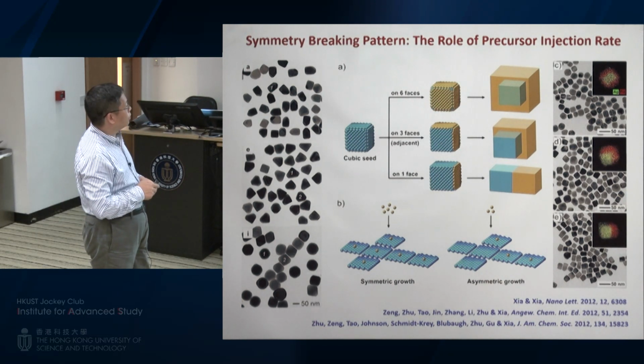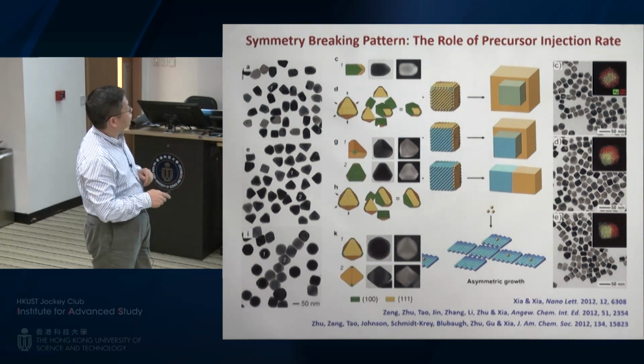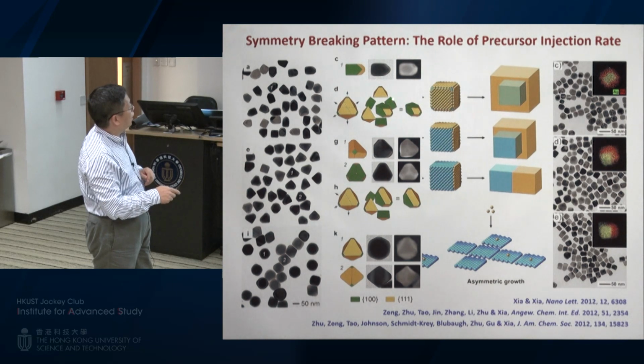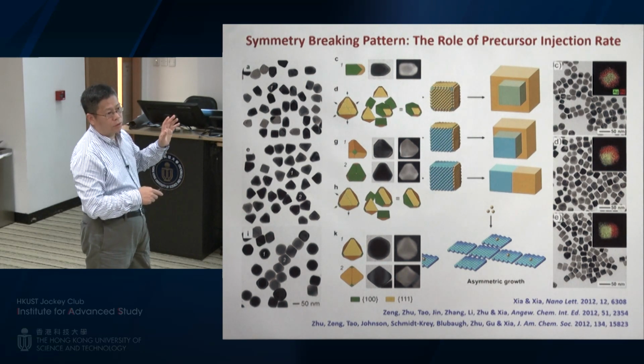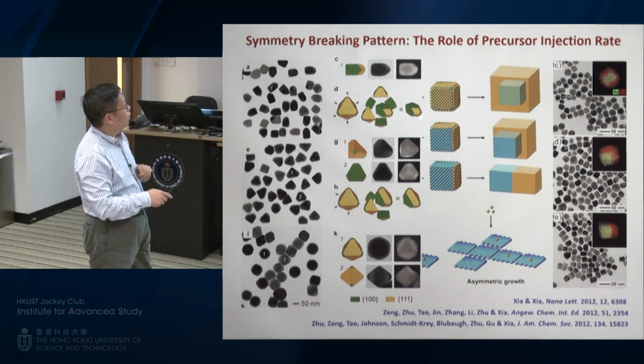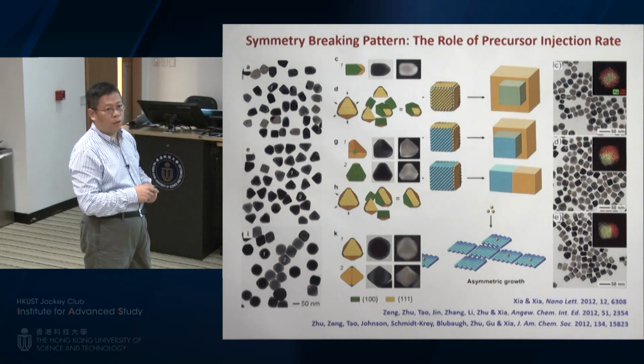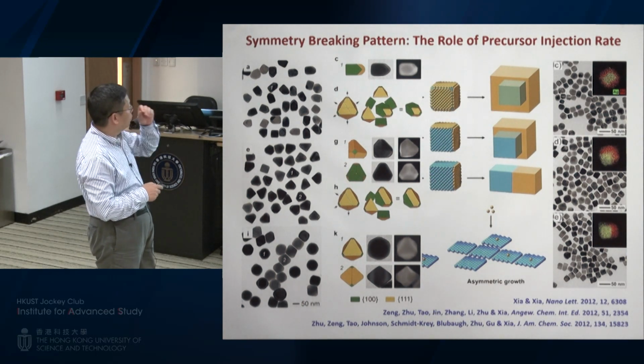Under certain conditions, like shown over here, you have slow injection of precursor, and the symmetry will be broken in such a way that you only have growth along one of the side faces. So in this case, all of these other 5 directions are not allowed. They are not going to have growth. You only have growth along one of the directions. So that's why eventually it will give you the elongated rod-shaped or bar-shaped nanocrystals.